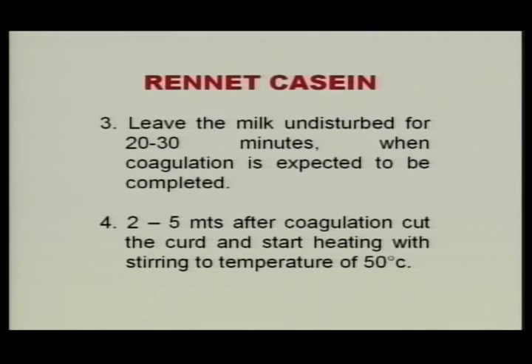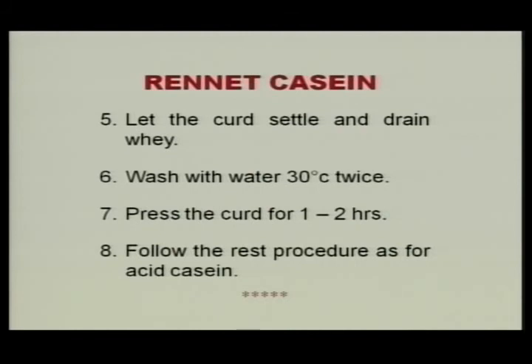Add the rennet solution and leave the milk undisturbed for 20 to 30 minutes, during which coagulation will be completed. After 2 to 5 minutes of complete coagulation, cut the curd using curd knives and simultaneously heat the coagulum with whey up to 50°C to recover maximum casein. Allow the curd to settle for a few minutes, drain the whey, then wash with water at 30°C twice. The total quantity of wash water should equal the quantity of whey generated.